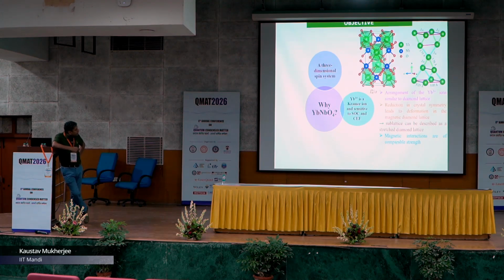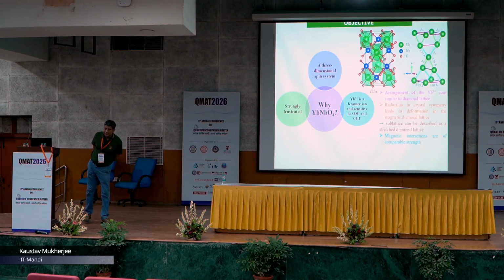So due to reduction in symmetry, what happens is that there is a deformation in the magnetic diamond lattice, and we get various bond lengths, J1L and J1S, of comparable strength or comparable distance. So this is a stretched one due to this distortion. So we are calling this sublattice a stretched diamond lattice, and in this stretched diamond lattice the magnetic interactions are of comparable strength. So this system is a strongly frustrated system.